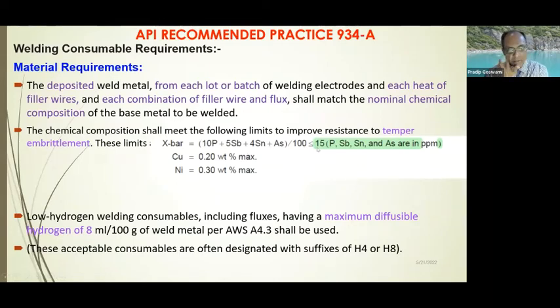That's a typical requirement. At the same time, low hydrogen consumables have to be used. That is a well-known fact. The diffusible hydrogen should not be more than 8 ml in 100 grams of weld deposit. And typically, all the welding consumables used for this intended application are either H4 or H8 grades.